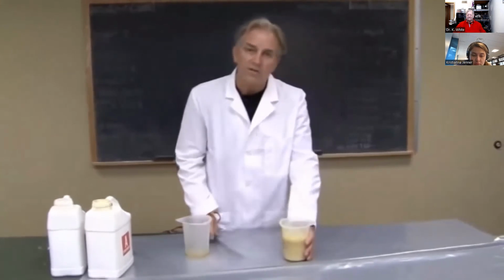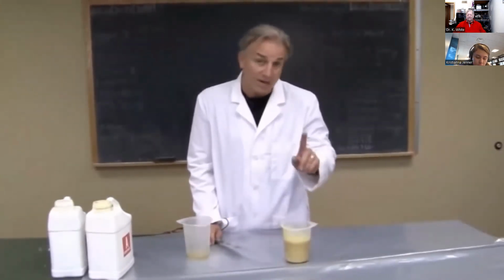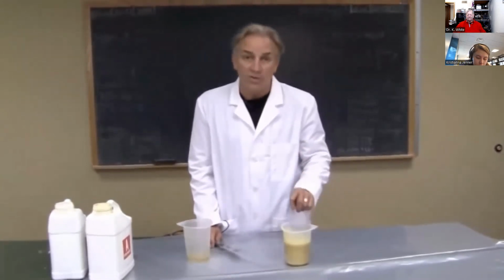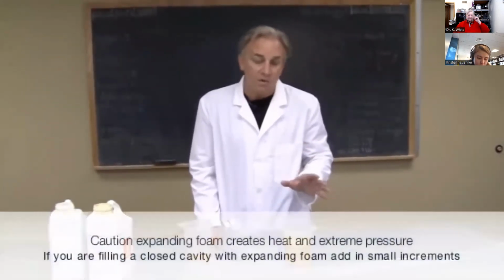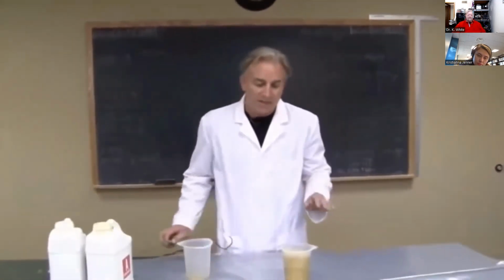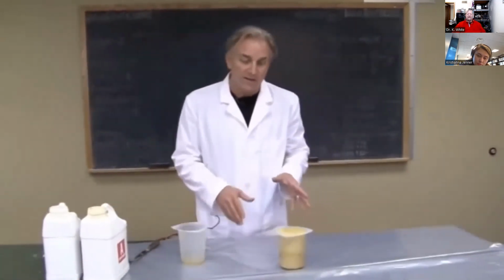It gives you about a minute or so of time to actually mix the foam and pour it into the mold. You got to be careful now not to put too much foam into a closed cavity mold, because it does create quite a bit of pressure on its own, and it could warp your mold. So now it's starting to come up, and actually to demonstrate this, we're just going to let it come up to kind of show you what we call free rise. See it rising?